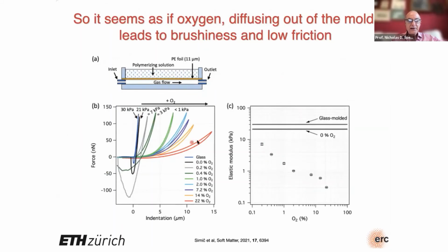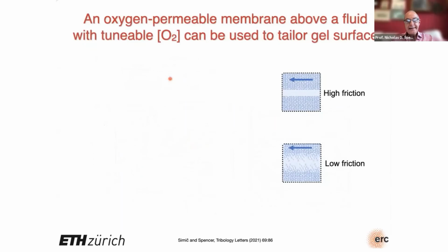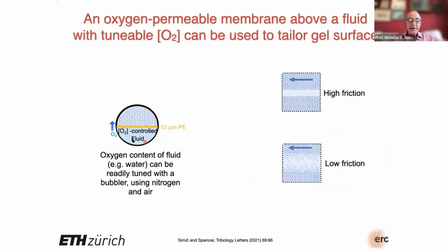Depending on how much is in there, that will control the elastic modulus and therefore the lubricity of the surface. This means that you can also use something like water down here, another kind of fluid, and use a bubbler to control the amount of dissolved oxygen. And then with a very thin membrane that allows oxygen to pass through, you can control the degree of dangling chains on the surface of the hydrogel. Therefore, by messing around with the oxygen content of the fluid underneath, you can choose low friction or high friction or anywhere in between. So you have a tunable lubricity.